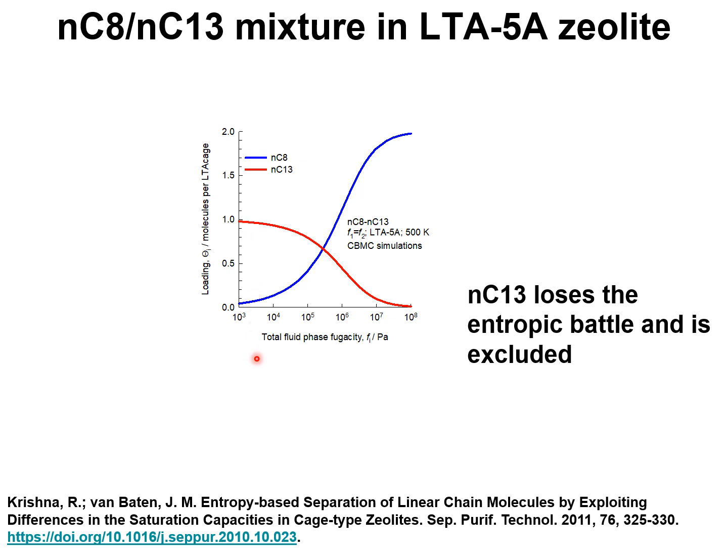However, as the total fugacity of the bulk fluid mixture increases and the adsorption occurs under saturation conditions, say at a total fugacity of 100 megapascals, the mixture adsorption equilibrium is entirely in favor of the shorter NC8, and the longer chain NC13 is excluded from the pores because it loses the entropic battle.